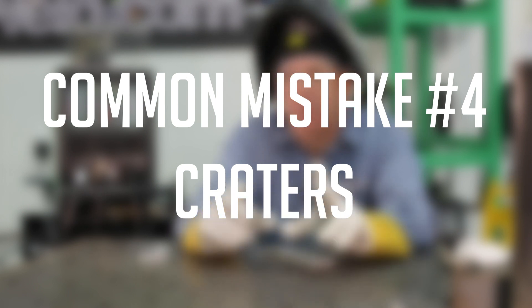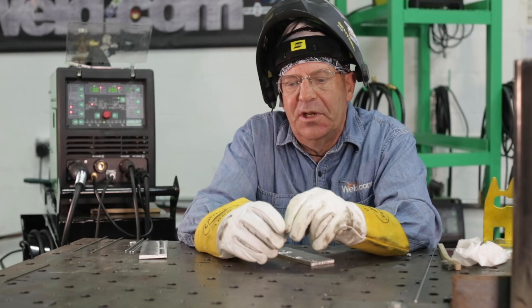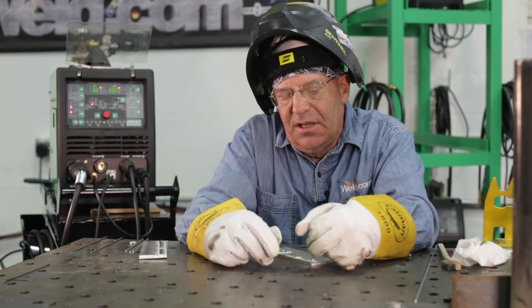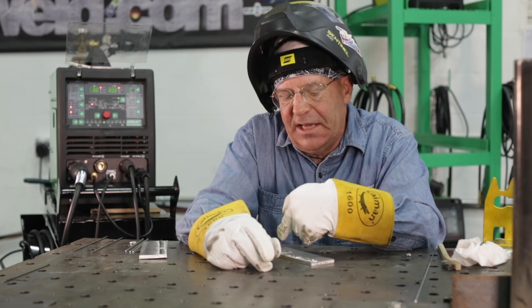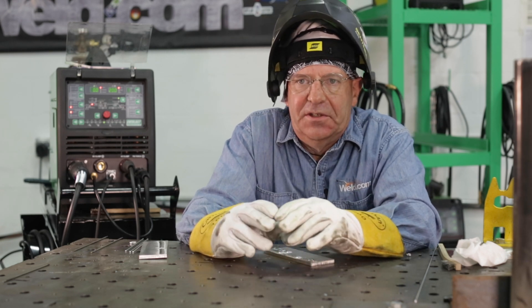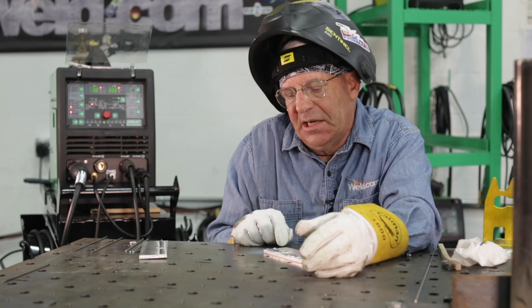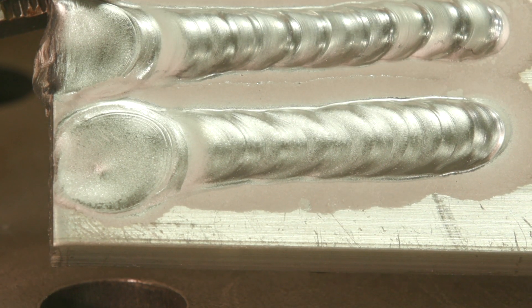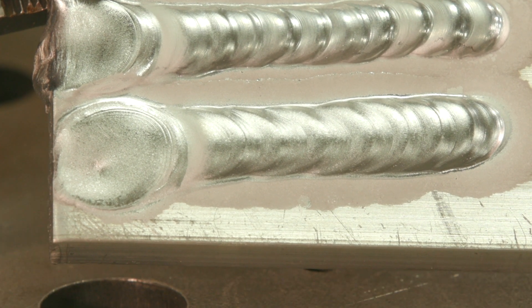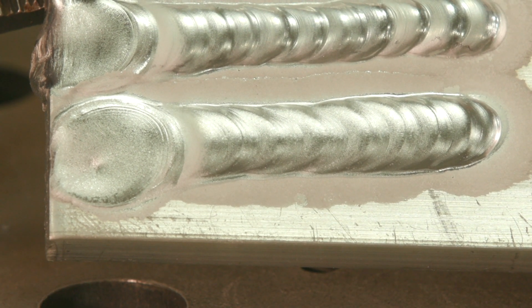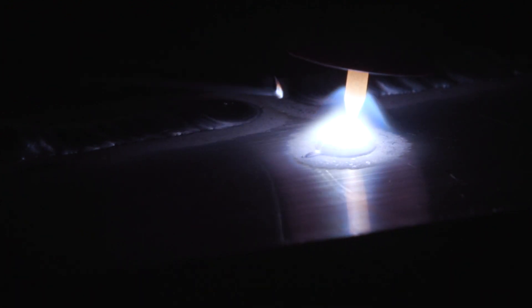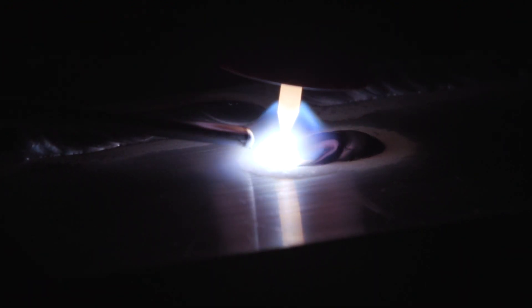Our next one is very common. I see this a lot, especially in aluminum welding, because it's real easy to terminate a MIG weld and just come out of it. I see it a lot in TIG welding as well, especially out on edges. A while ago I said that aluminum dissipates heat four times faster than carbon steel. You reduce your amperage when you come out here on the edge. I see a lot of people come out on the edge and their bead is real wide and flat, then they get out here and it's blown up. It's real easy to do. We ran the correct bead where we added wire. This one will be just the opposite. We're going to come out to the edge, stay on the amperage and just blow it up.